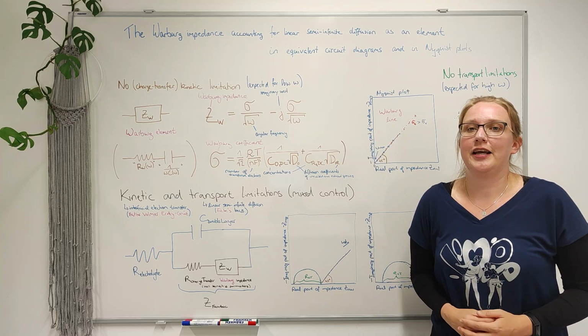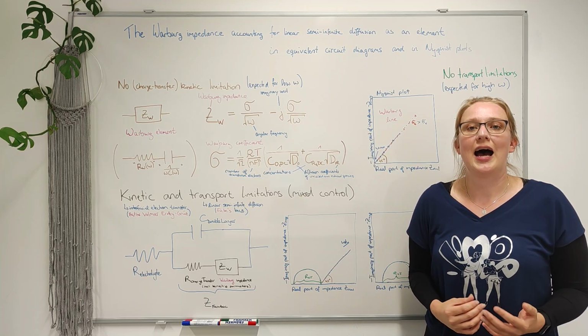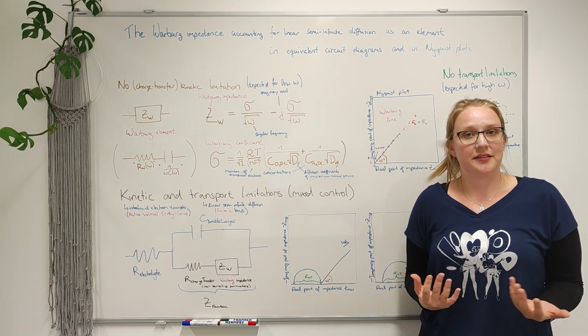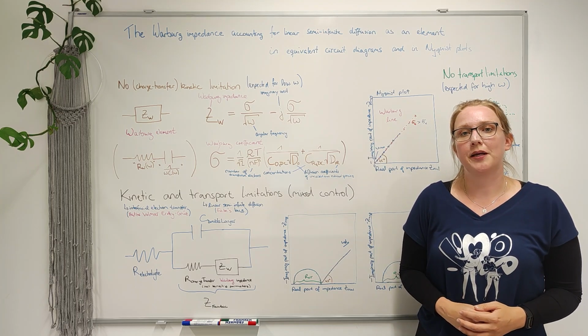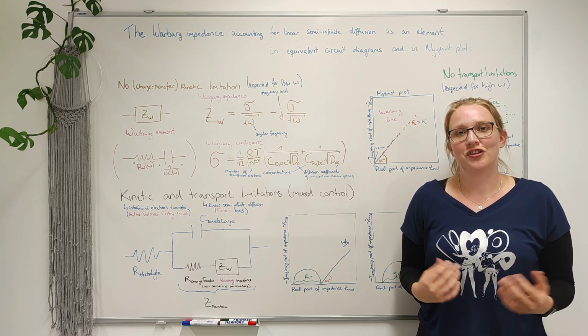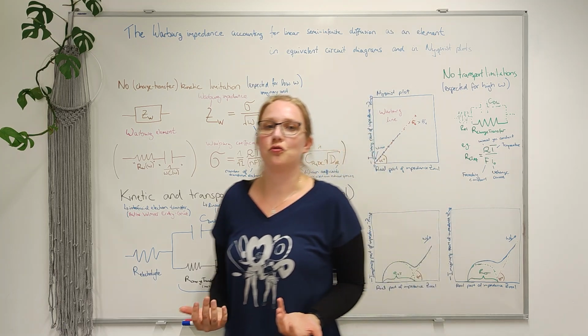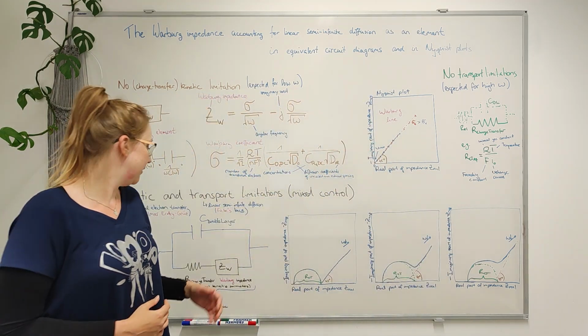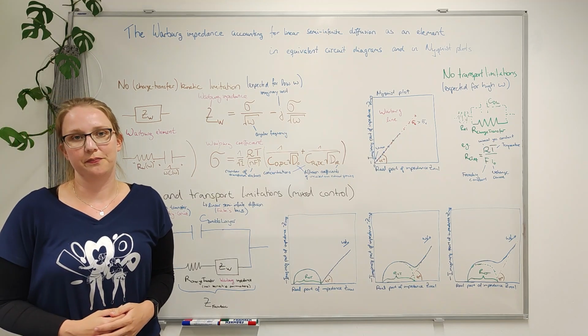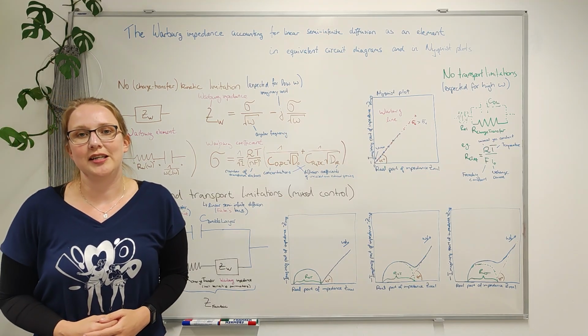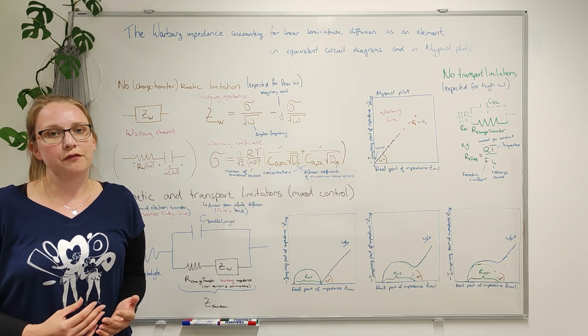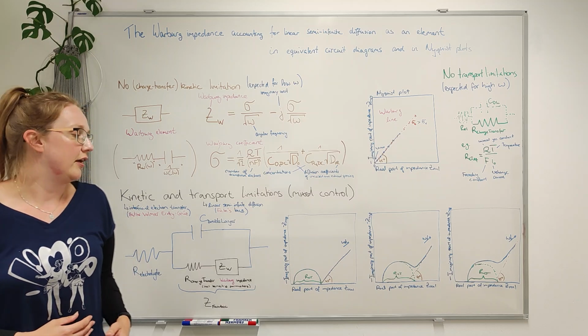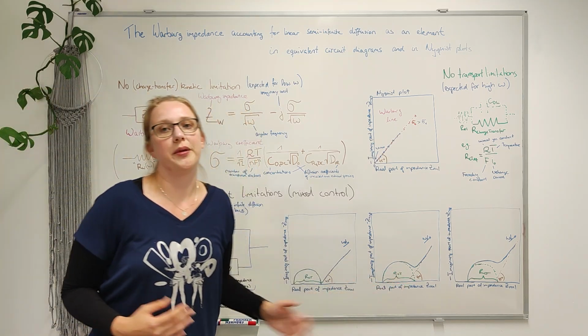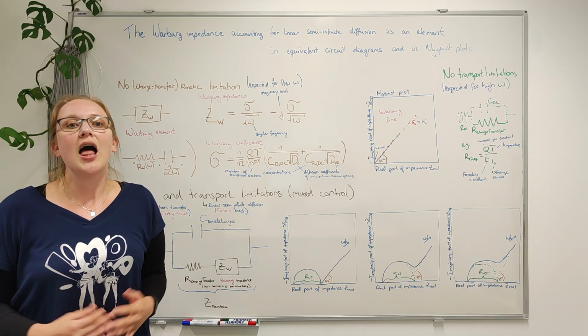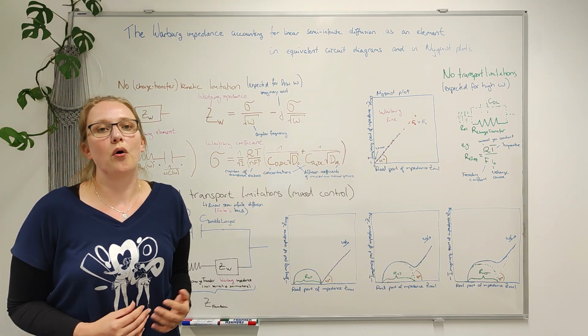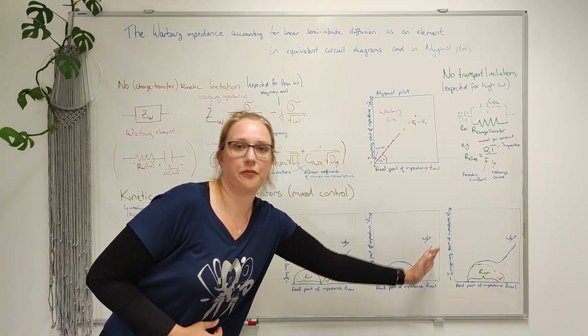In the impedance spectrum of an electrochemical reaction of a redox couple in solution, other influences can also be seen, such as the electrolyte resistance, which causes a shift of the impedance spectrum along the real axis. Fortunately, we can combine the equivalent circuit approach, which is based on electrical elements, with our new element derived from physico-chemical equations. When both electron transfer kinetics and diffusion hindrance are present, diffusion influences may vanish at high frequencies, where interfacial charge transfer predominates, forming a semicircle in the high frequency range. At low frequencies, the diffusion limitation gains more and more influence. A Warburg straight line is observed.